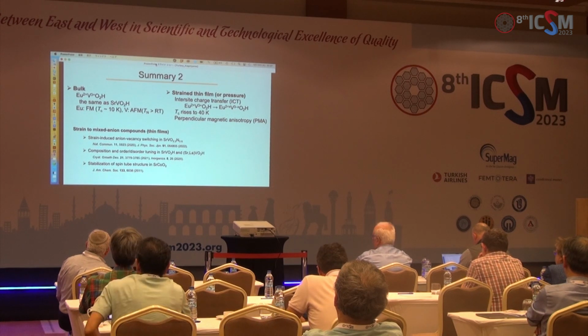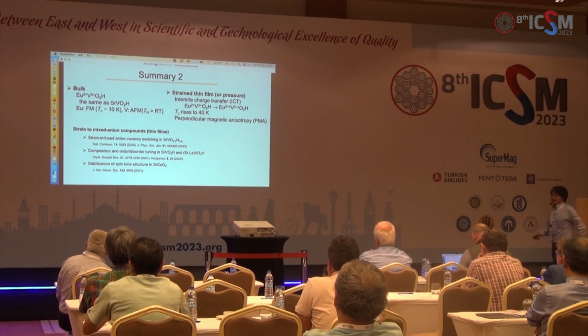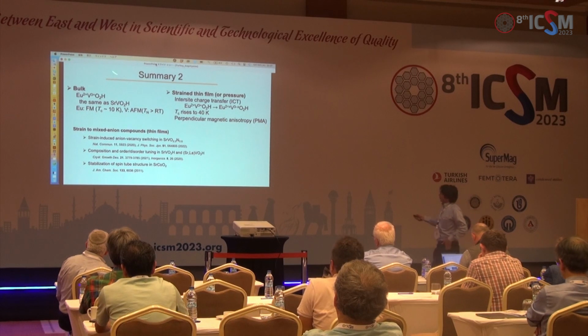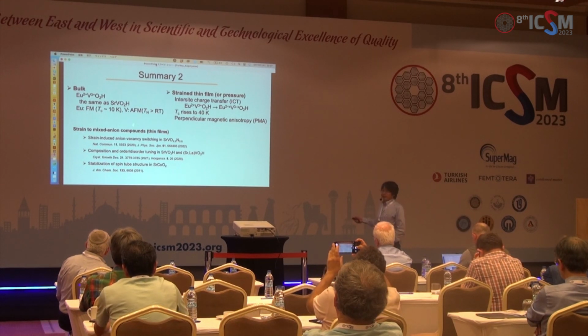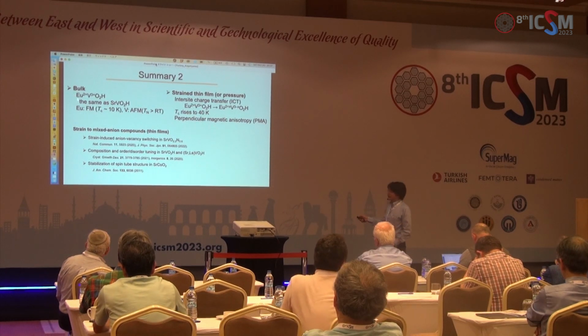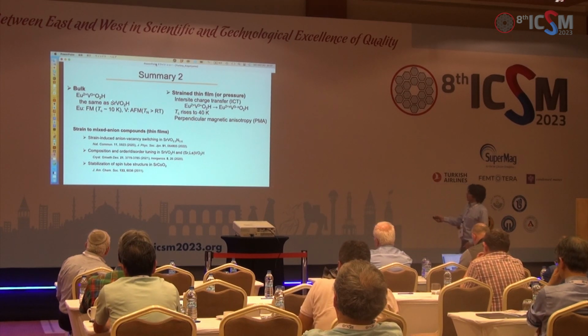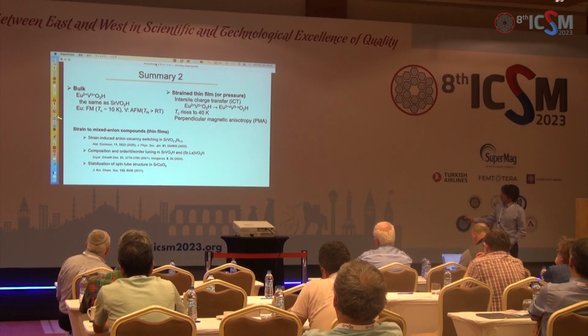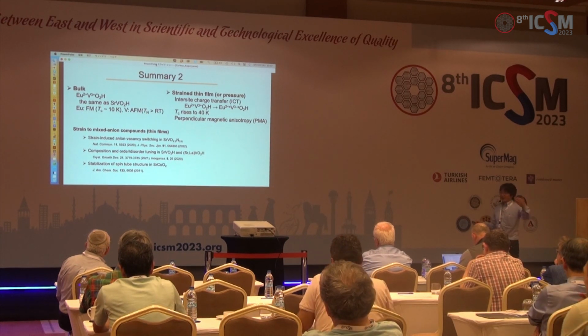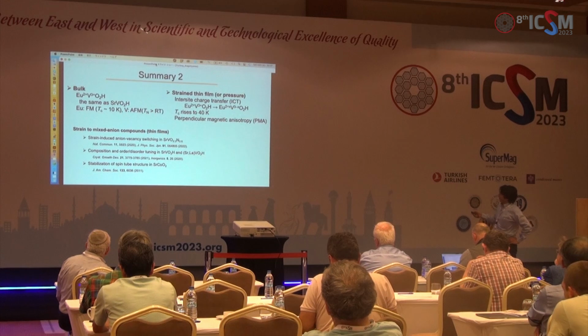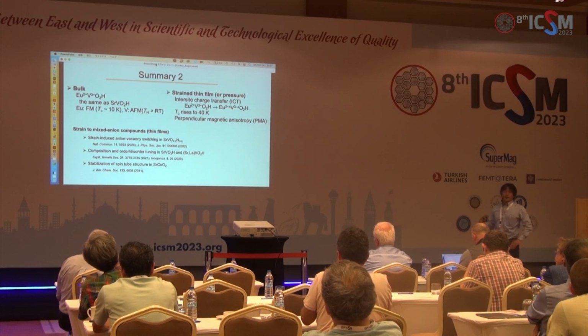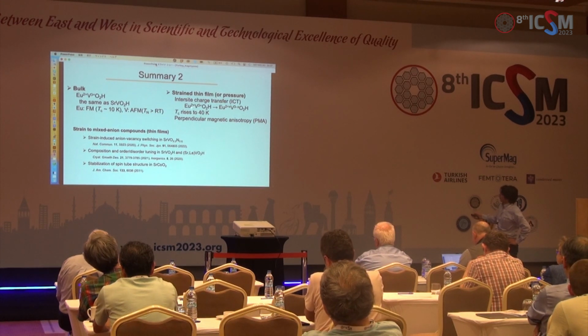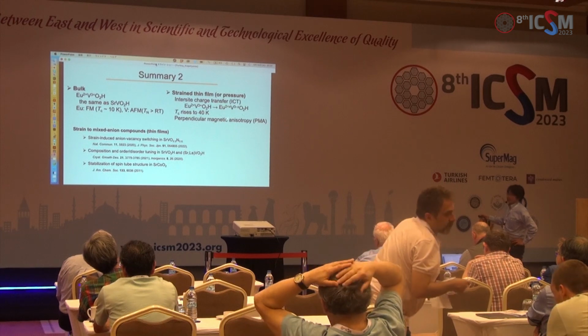So let me summarize the second part of my talk. So we obtained this new material, EuVO2H, which has an Eu 2+ state and is not an insulating state, but Eu has shown the ferromagnetic transition. But when you apply the strain, I mean compressive strain or external pressure, you can induce intersite charge transfer.